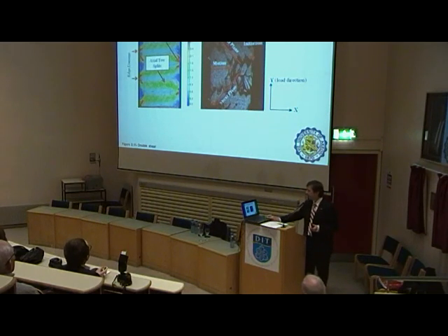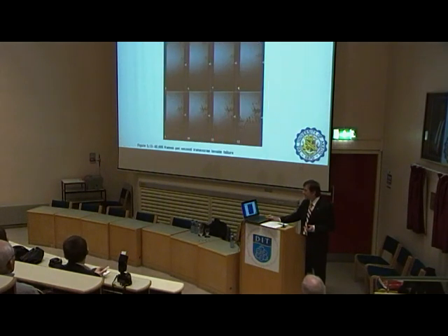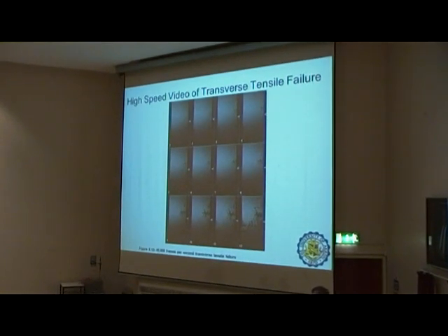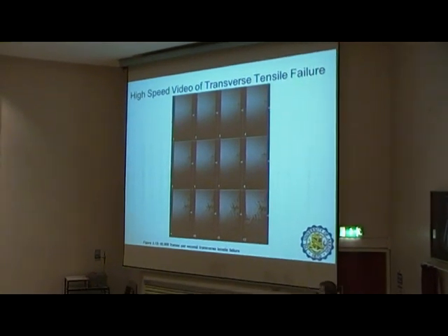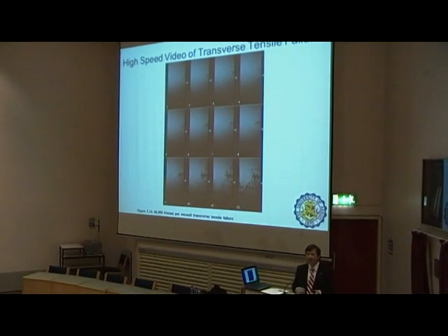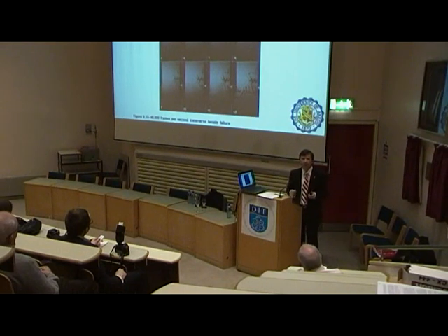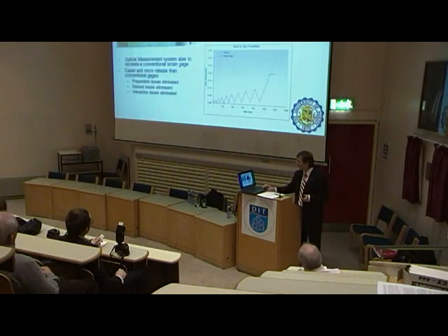And again, a lot of tests show the mode of failure under tension, and these are pictures from the high-speed cameras that show how quickly it happens. This is 40,000 frames per second, so within 12 frames of the 40,000 frames per second, you can see the damage progression. You have to capture that very quickly, otherwise you don't see it at all.